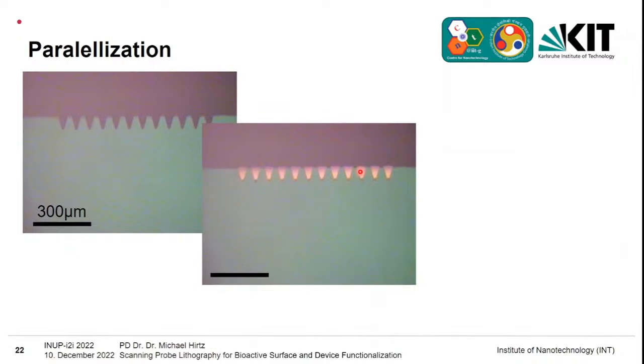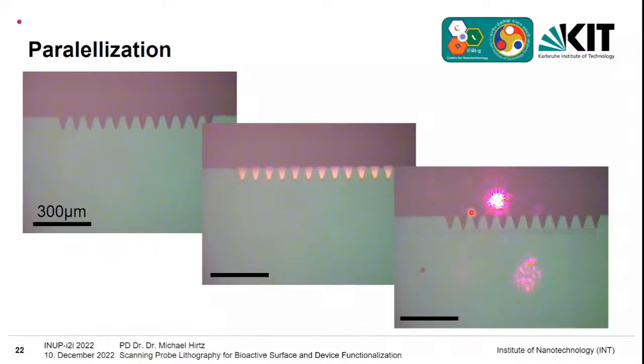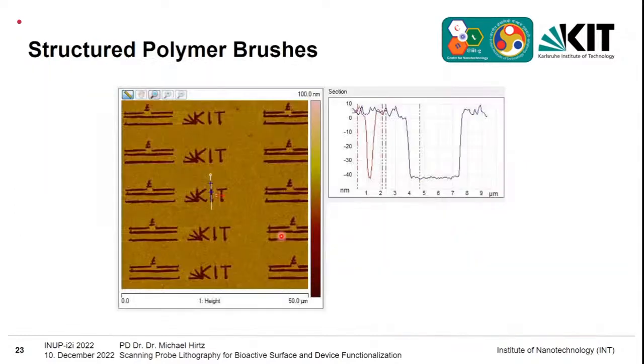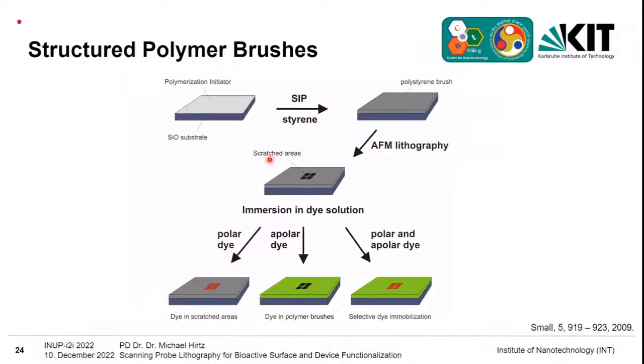You can parallelize this. And so instead of only using one tip, you can use 1D arrays of tips, as you can see here. So now they're in contact, they're bending a little bit. That's why they change in color. And finally, you can write a pattern. So you can see here maybe the little bit dark things. And if you look at this again with AFM, you can see different logos from University Münster and the KIT. And again, you can scratch fairly nanometer-sized films, like here up to 50 nanometer films, with this kind of arbitrary patterns.